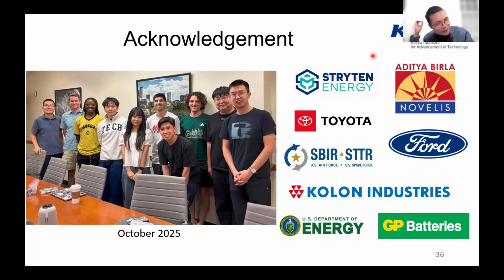Yeah, so for the flow battery, the electrolyte will degrade over time, and some are regeneratable, like vanadium. You can do a rebalancing. Basically, you mix the two tanks together so they reach the same oxidation state, and then you charge one side and discharge the other side to remake the catholyte and anolyte, and that will be enough to regenerate them. But for some other flow battery chemistries, for example the organic one or the iron one, that don't have the same species on the two sides, you can't do this kind of regeneration. You have to go through more steps to regenerate them.